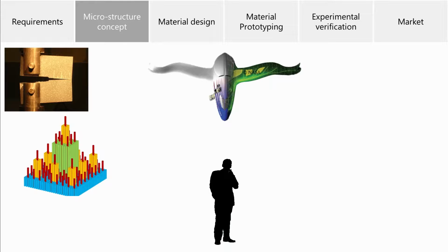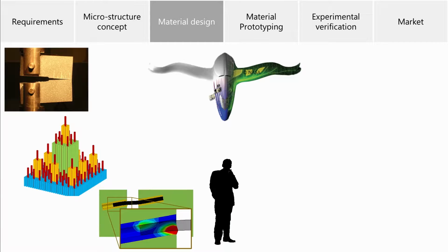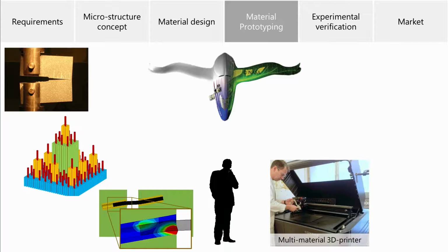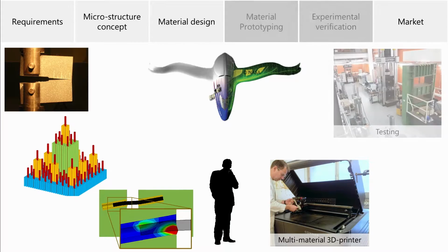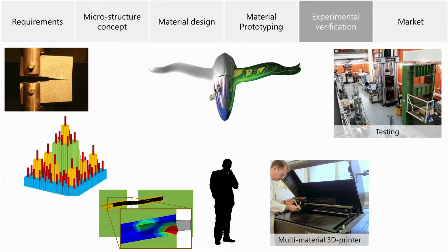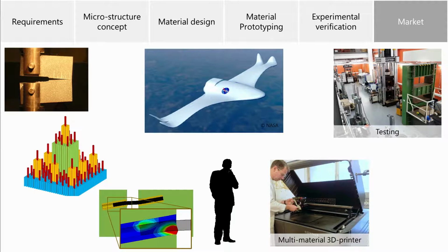Then you would think of a concept for a microstructure that could be suitable for that type of requirement. So if you are talking about resisting cracks propagating, you might want to have fibers in a direction perpendicular to that crack, organized in such a way that they have to pull out from both sides of the fracture surface, therefore dissipating a large amount of energy as they do so. And then you'll use numerical methods, such as the ones that I've shown or others, to actually design the details of that microstructure. Then using additive manufacturing, for instance, that Alan mentioned before, you could create prototypes for those materials, verify experimentally whether they work, and then hopefully finally create a product that you can put in the market.